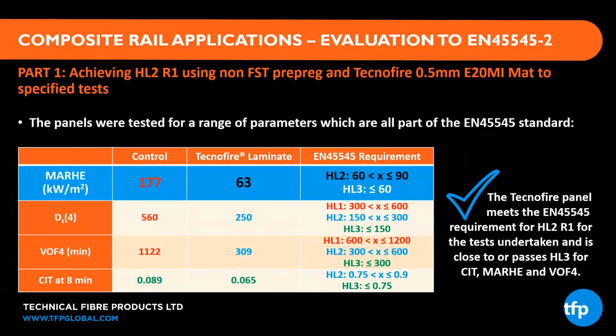For the control non-FST rated laminate, the MARHE result was 177, shown above in red, which is pretty high. However, by simply incorporating the 0.5 millimeter layer of Technofire onto the surface before compression molding, this result has been reduced to 63. An improvement or reduction in heat release of 65%, or 2/3, by simply dropping in this thin layer of Technofire.